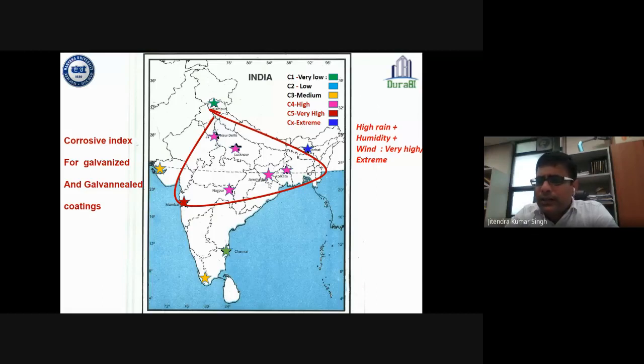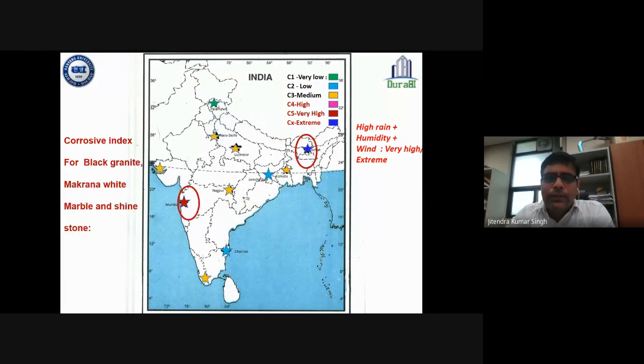Jamshedpur has sulfur dioxide content, carbon content, and particulate matter. Kolkata has humidity, so that's also affecting the corrosion rate. But as we move to Jorhat, it is low. And once you move to Palanpur, there is no corrosion. There is very little corrosion due to the virgin condition.